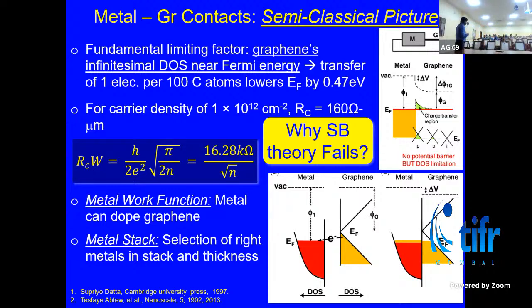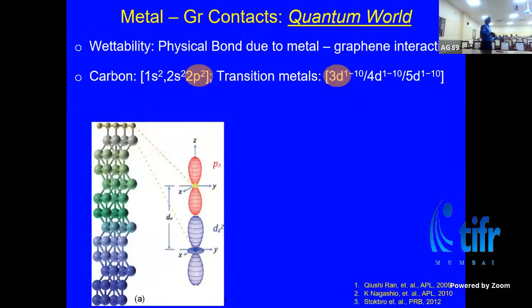There were a lot of reports of the room temperature contact resistance and the low temperature contact resistance, and the low temperature contact resistance was always better. We questioned that: if there is Schottky barrier theory involved here, then why does the low temperature contact resistance have to be lower than the room temperature contact resistance, which should be higher, right? Because I'm taking energy out of the carrier, I'm making the carrier put in more effort to cross the barrier. So then we also started investigating.